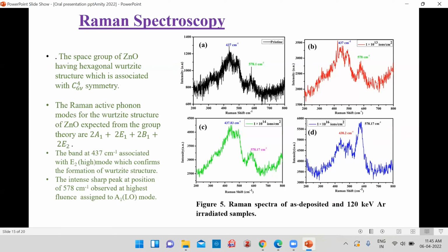This is the Raman spectra. From the theory, we have ZnO having a hexagonal Wurtzite structure, which is associated with the C6v symmetry. Raman modes for Wurtzite structure are 2A1 plus 2E1, in which optical modes and acoustic modes are included. We have seen from the figure two modes observed at 437 centimeter inverse and 578.1 centimeter inverse. The 437 is due to the E2 high mode, which confirms the formation of the Wurtzite structure.